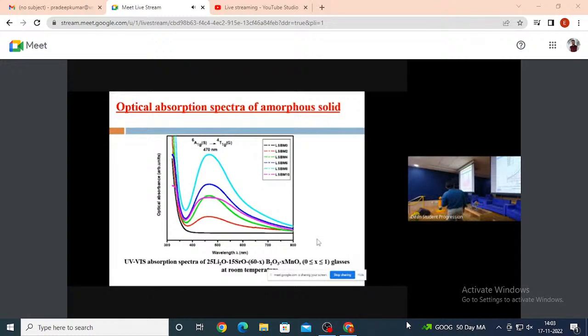Here the position of this band was found to be shifted. Shifted means the position of this band was displaced towards the higher wavelength side from 0 to 0.8 mole percent of MnO, and later the band was blue shifted, that is, shifted to the lower wavelength side. So the shifting of these bands to higher wavelength sides from 0 to 0.8 mole percent of MnO represents an increment in the octahedral Mn2+ ions at the expense of octahedral Mn3+ ions.